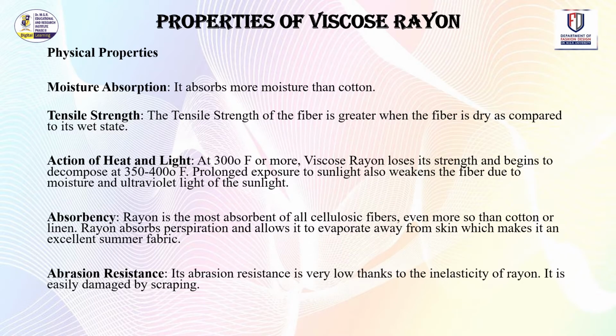Properties of viscose rayon. Physical properties: moisture absorption. It absorbs more moisture than cotton. Tensile strength. The tensile strength of the fiber is greater when the fiber is dry as compared to its wet state. Action of heat and light. At 300 degrees Fahrenheit or more, viscose rayon loses its strength and begins to decompose at 350 to 400 degrees Fahrenheit. Prolonged exposure to sunlight also weakens the fiber due to the moisture and the ultraviolet light of the sunlight.